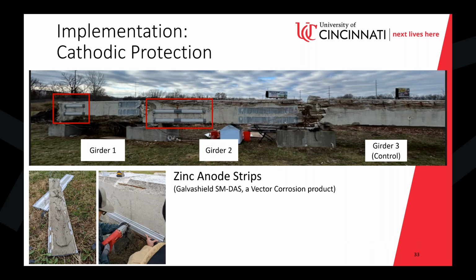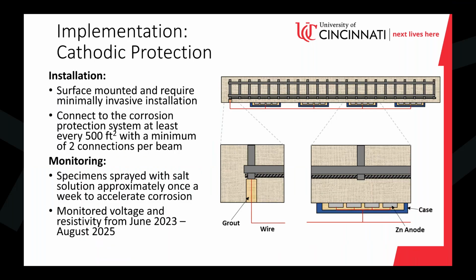We tested, we had three girders. We kept one as a control, two were cathodically protected. You can see here, each one of them was protected on one side by these strips, on the other side by the zinc sheets. And we set up, you can see underneath there, the little doghouse and all these wires running around. We set up a monitoring system so we could evaluate how well the cathodic protection was working, as well as some in situ resistance monitoring I'll talk about next. But the installation is really a surface mounting, and then at some point you need to connect it to the steel. So that would be, again, drilling to the steel and grouting behind it afterwards.